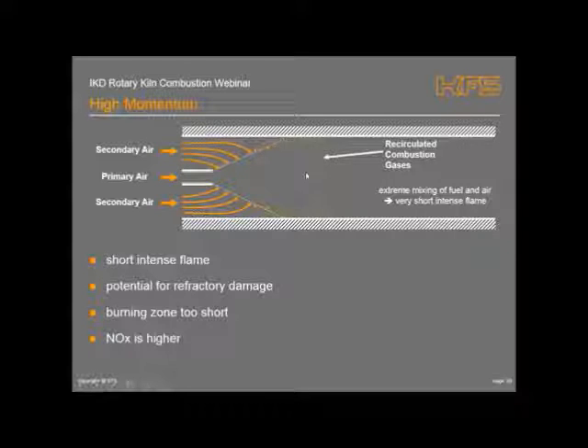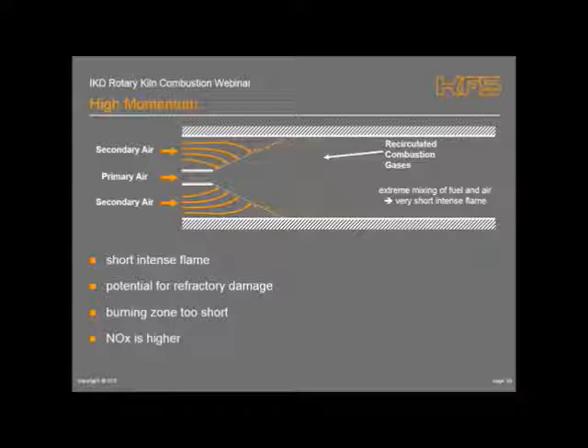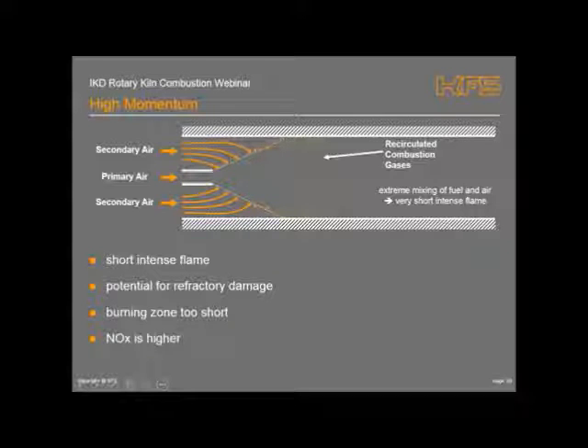In this area, you have relatively high temperature gases, so you're drawing hot gases back into the flame, which can help stabilize it. But with excessive high momentum, you're brushing hot gases across the refractory, which can lead to thermal damage. Also, the products of combustion are steam and CO2 - anybody who's done firefighting techniques will know that steam and CO2 are very good flame suppressors. Hence, it can lead to flame instability, starving oxygen in certain areas. It does create a short, intense flame, but there is potential refractory damage, burning zone too short, and NOx is higher.